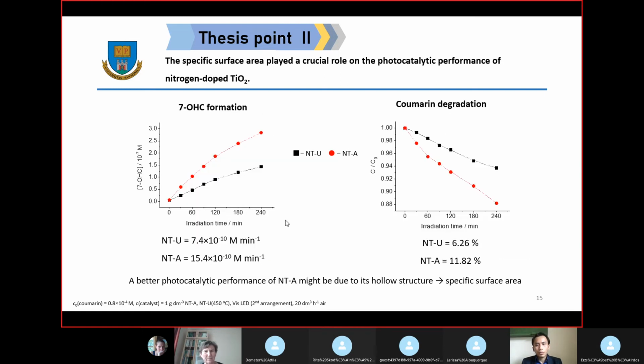We also studied the photocatalytic activity in the coumarin solution. From this figure, we see that the hollow structure produced a higher 7-hydroxycoumarin and also a higher coumarin degradation. This better performance may be due to the hollow structure and also, as we mentioned before, a higher specific surface area.